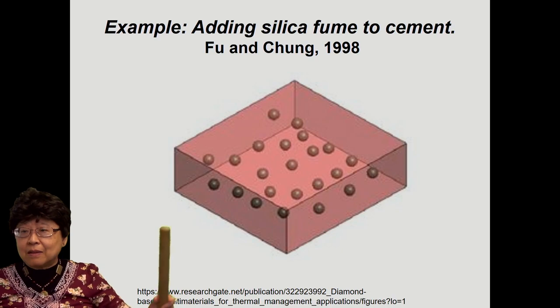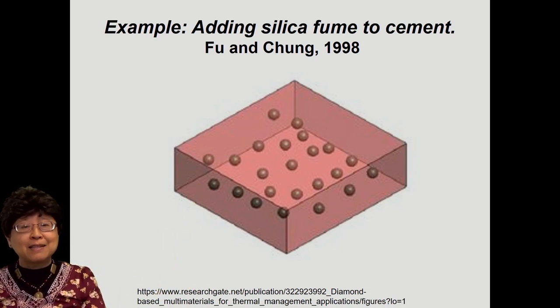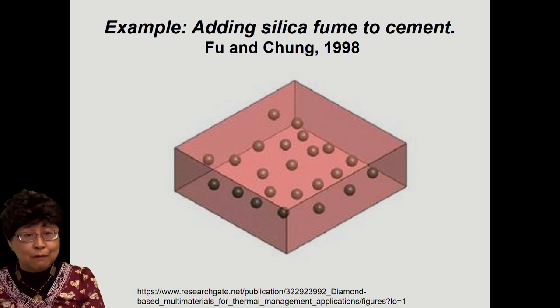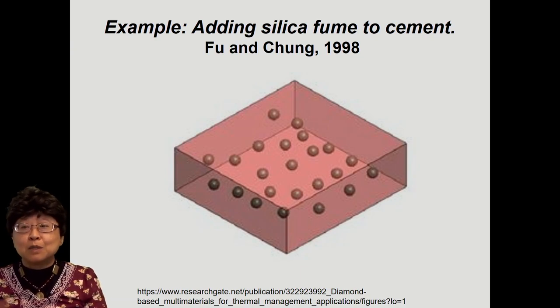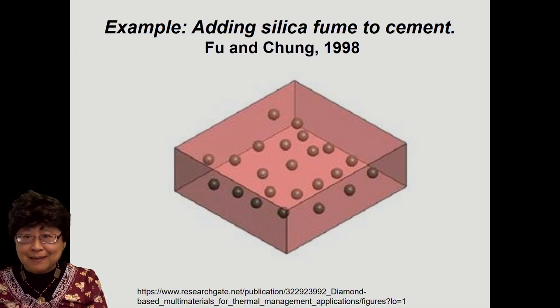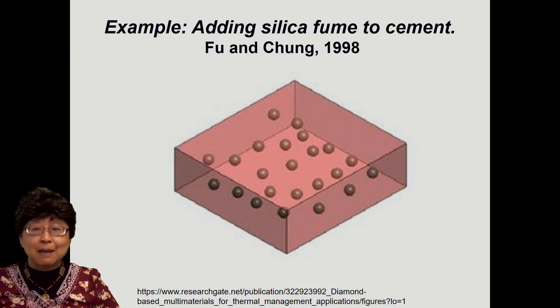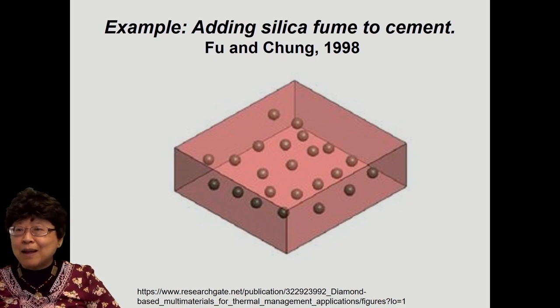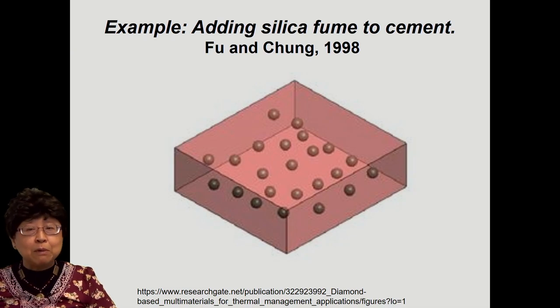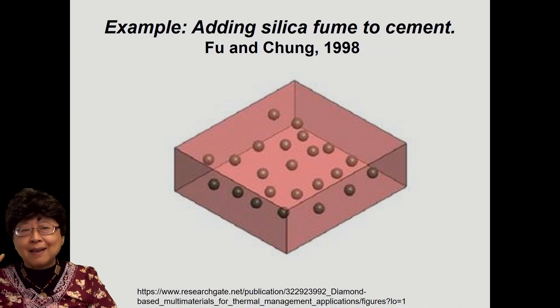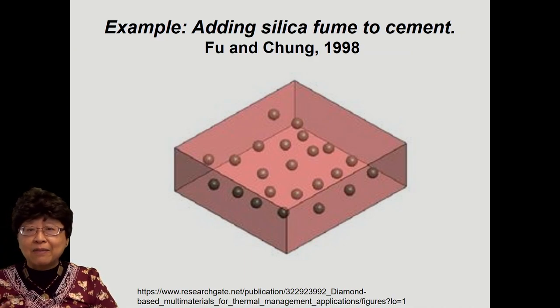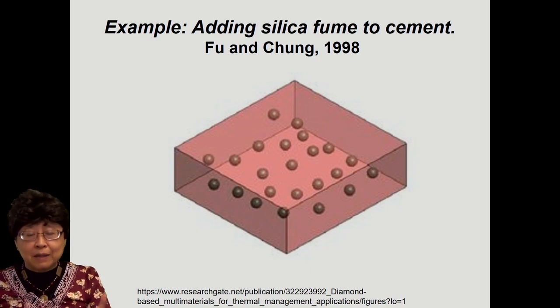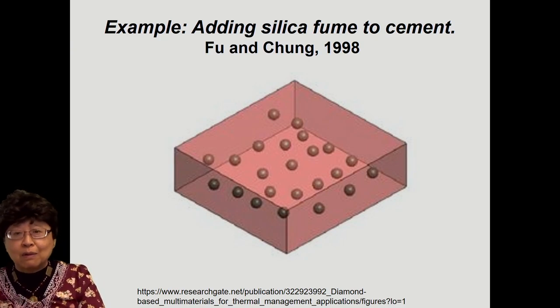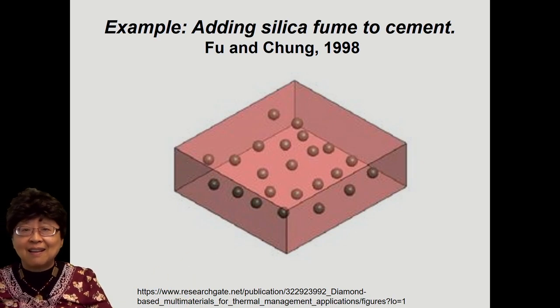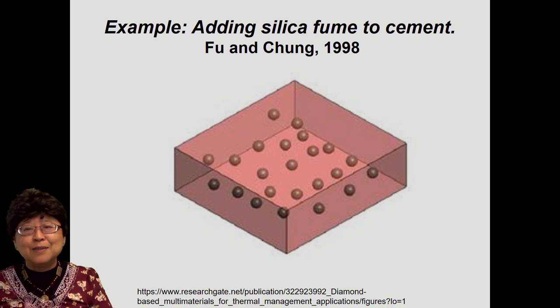But at the same time, the silica fume addition strengthens the material, makes it stiffer and stronger, because the silica fume is a reinforcement. So the material becomes stiffer, and at the same time, it becomes more viscoelastic and more able to dampen, having both aspects improved by the addition of silica fume. When I first presented this in 1998, people just could not accept it because they were thinking along the line of rubber. If you modify rubber so that it becomes stiffer, it would have less damping ability. You gain one and lose the other. You cannot have both improved at the same time. So this involves a different science, and people were not used to this new science.